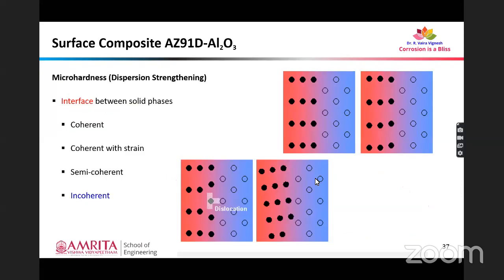And the hardening mechanism in a surface composite could be elaborated based on the dispersion strengthening phenomenon. Generally speaking, the interface between the solid phases determines this dispersion strengthening effect in composites or even in alloys. So we have coherent interface, coherent with strain, semi-coherent, and incoherent interfaces.